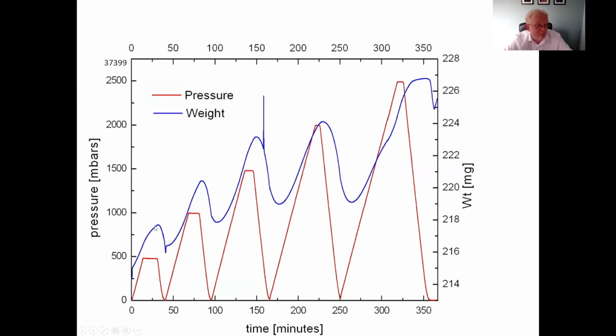So if we use a different pressure regime, we can see how the weight changes on each hydrogenation cycle. And see, as we increase the pressure, unremarkably, the weight increases, indicating that we've increased the amount of amide formed on each pressurization step.